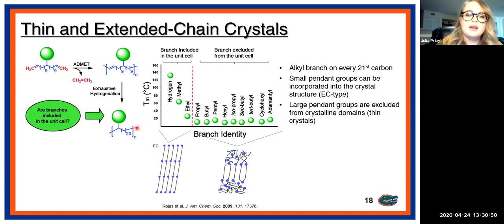And we used this to then compare the melting point of all these different precision polymers. So when the functionality is a hydrogen, methyl, or ethyl group, the melting point is higher than all of the rest of the functional groups that you can have. So for hydrogen, it has a melting point of about 135 degrees Celsius, which is what we would expect for linear polyethylene. The melting point is significantly lowered when you put a methyl group on every 21st carbon, and then lowered again if you put an ethyl group. And then after that, the melting points stay fairly similar.